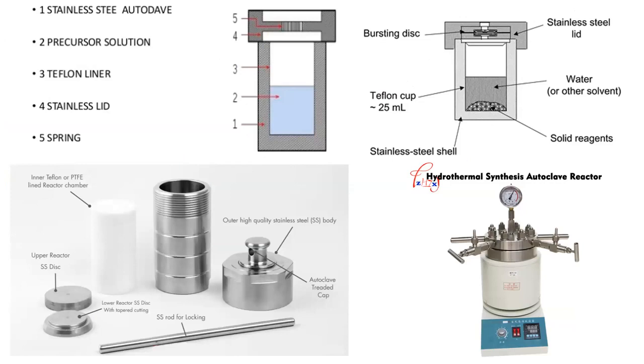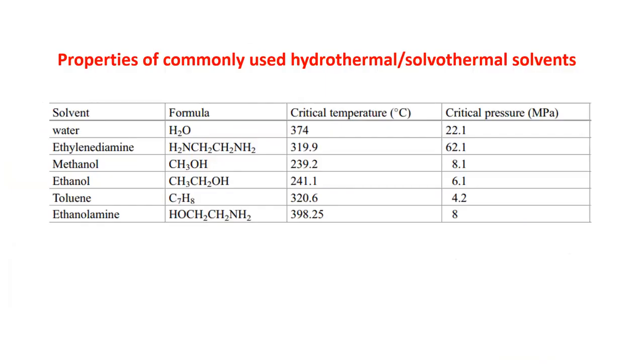Simply, it is a suitable Teflon bomb. We can control pH, pressure, and temperature of this system. If we use water, this system is called a hydrothermal system. And it's also possible to use different solvents, for example, ethylene diamine, methanol, ethanol, toluene. You can use different solvents for this Teflon bomb system, and the methodology is generally called the solvothermal methodology.